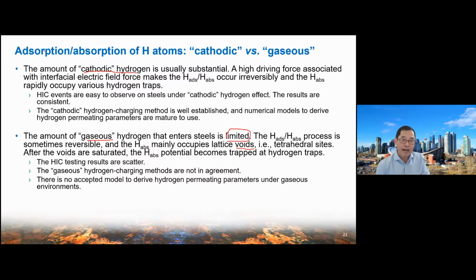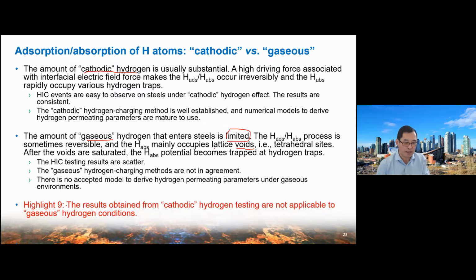So that's why hydrogen from the cathodic source and from the gas source have a totally different hydrogen permeation process. That also tells us a very important conclusion. If you have results you got from cathodic hydrogen testing, I know there is a lot of testing in this area, unfortunately, the results cannot directly apply to gas phase hydrogen. So this does not apply directly, and you have to develop a new testing method and a new model to derive the hydrogen permeation parameters in gaseous conditions.